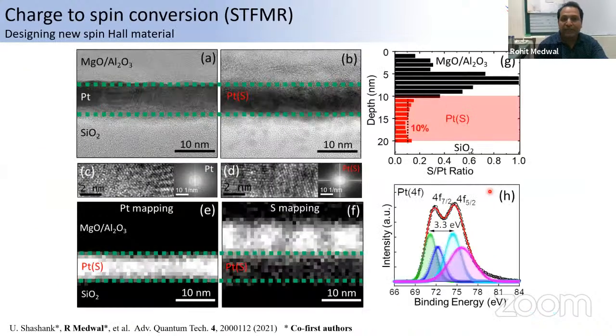What we did initially with the TEM, we have this precession TEM. So we have a platinum, we did the 10 nanometer platinum. We implant the 10 nanometer platinum with sulfur, keeping the same thickness. So after implantation, our thickness is not modified, it's almost the same. We did the electron energy loss spectroscopy to see the percentage of sulfur being implanted in the platinum.